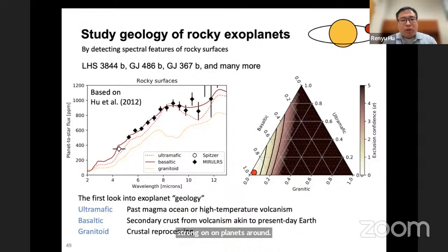So for these bare rock planets, I pointed out in 2012 that their surfaces are detectable through prominent SiO features in the thermal emission band between 7 and 13 micron. This kind of measurement was inspired by the success of using thermal emission spectroscopy to characterize the surface mineralogy and geology of rocky bodies in the solar system, such as the Moon and Mars and many other rocky bodies. And in 2012, I proposed that this method can be applied to rocky exoplanets without any atmosphere.